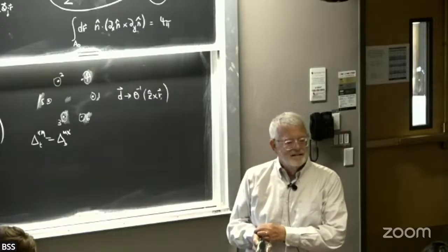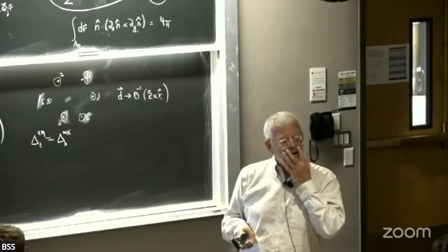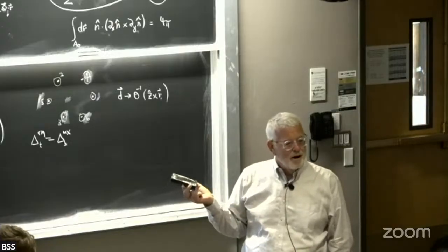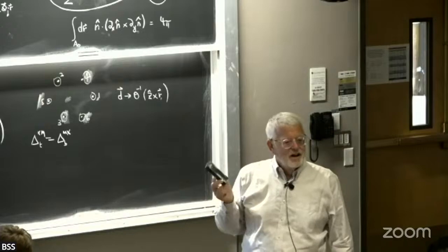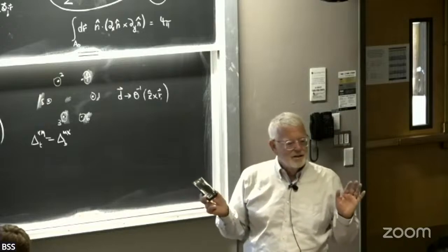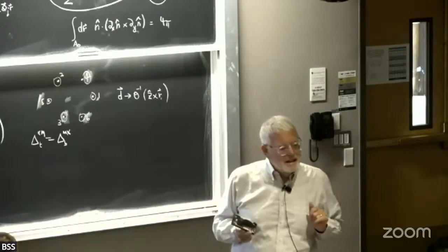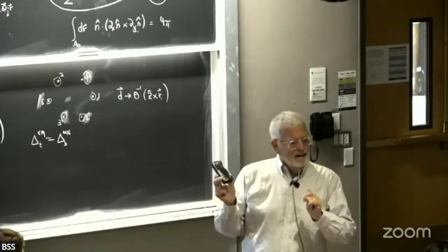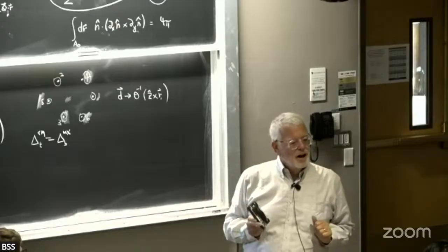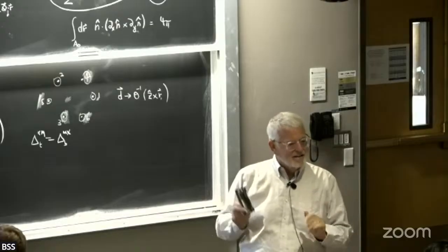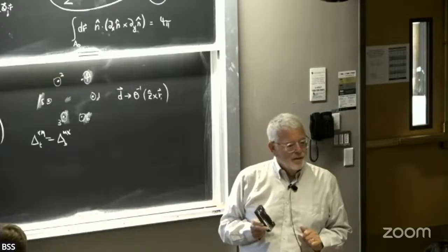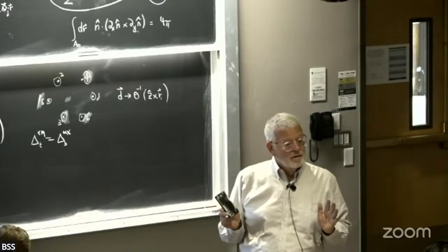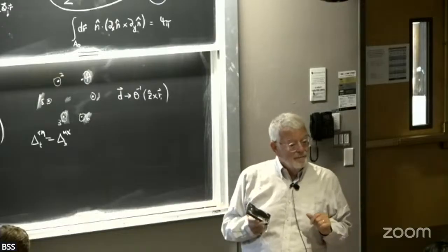Yeah. And the phenomenological approach, just using the high symmetry points, since the number of parameters is so small, works perfectly fine. Just like in the graphene case, there are lots of questions of detail about the DFT. One of the most important is strain relaxation on the Moiré scale, which I'm not discussing here. That turns out to be important when the Moiré period is very long.